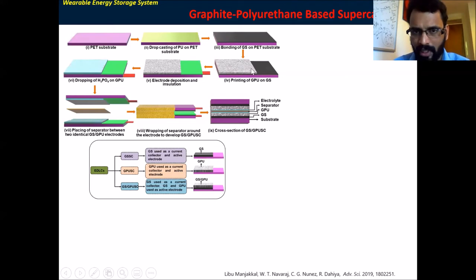And here I printed that conductive material on top of this graphene sheet. In a traditional supercapacitor, a separator is used in between the electrodes. So what I did, I wrapped the separator around the electrode. For enhancing supercapacitor performance, wettability is one of the critical factors. If your separator is always wet and keeps electrolyte for a long time, you can improve your performance or life cycle. So I used a cellulose polyester blend. It's a cloth, so it can always stay wet and easily hold the electrolyte for a long time.